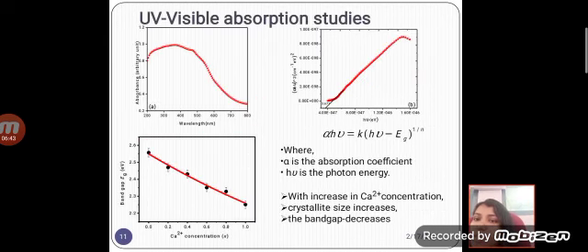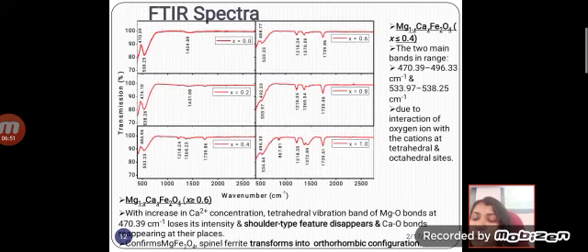The UV visible absorption studies show a decrease in band gap with increase in calcium concentration. And then moving to the Fourier transform infrared spectra, the peaks corresponding to ferrites, like iron oxide and oxygen vibrations, are found in the FTIR spectra of all the samples.